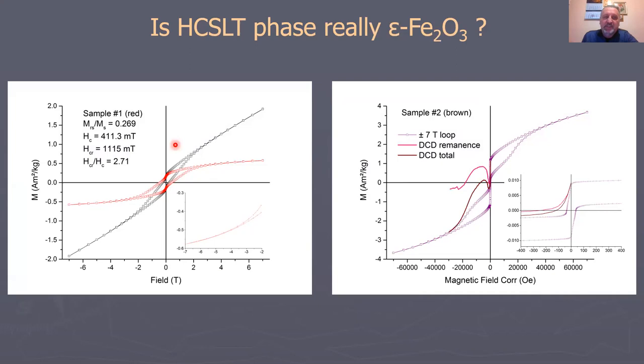Coercivity is high, but not as high as you would expect for perfect synthetic epsilon phase. Coercivity of remanence is also quite high, and higher than we normally see in ceramics, but otherwise this sample resembles a little bit the behavior we saw in the ceramic samples. But the brown sample is an enigma for us at the moment, and I plotted it here just to show what could happen.